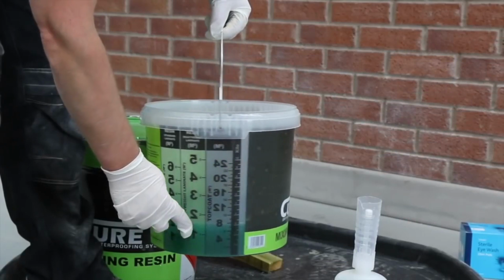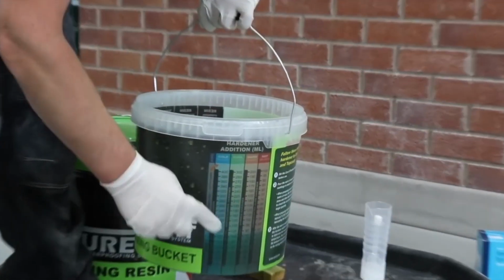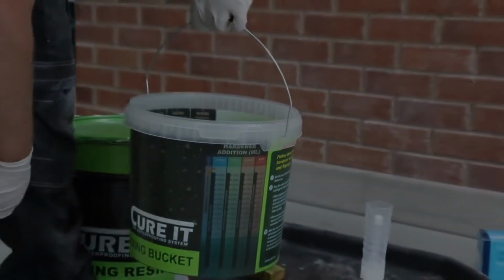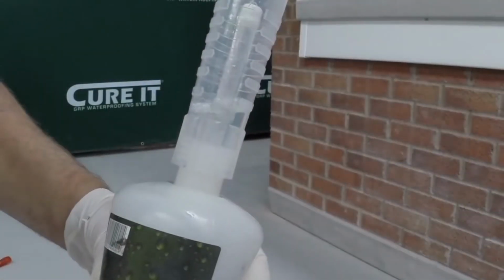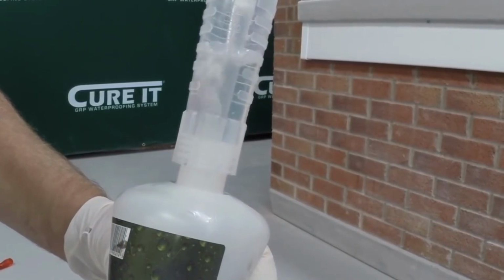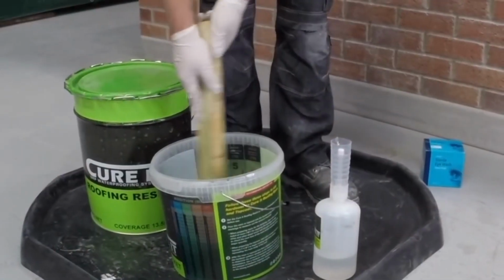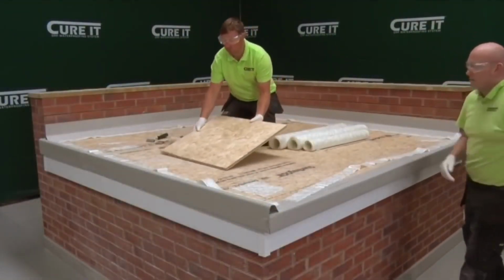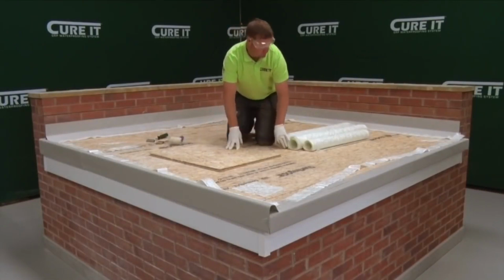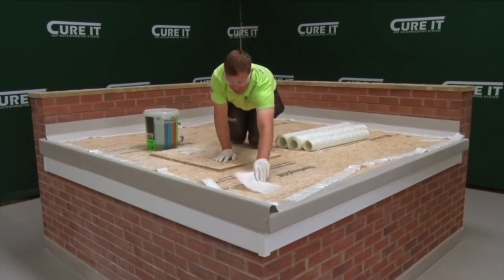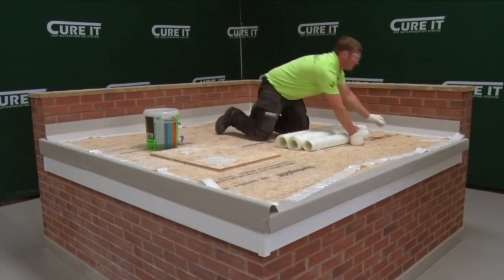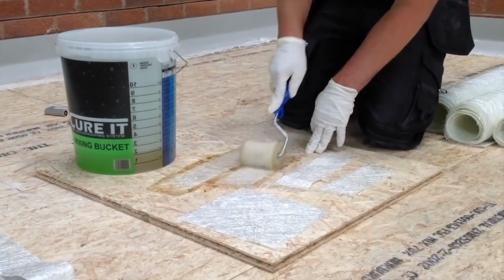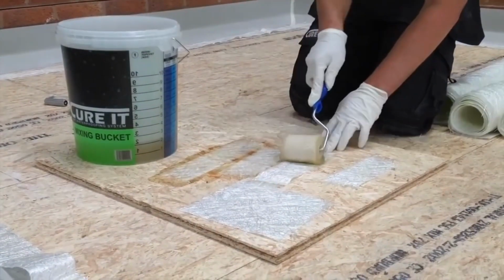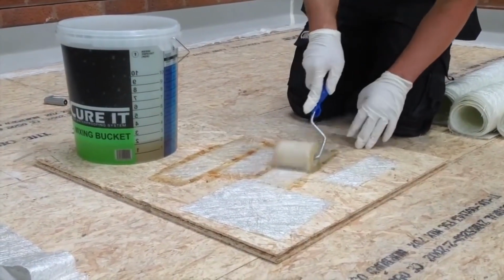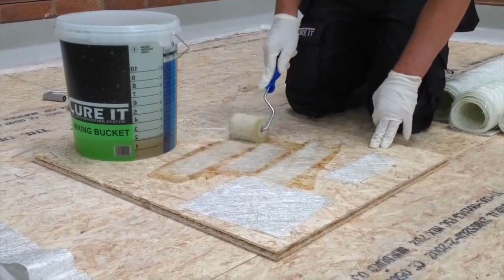Using the hardener addition chart on the side of the mixing bucket and factoring in the decking temperature and ambient conditions, measure out the required volume of hardener using the safety dispenser and mix thoroughly into the resin using a slate batten for at least 30 seconds. Set aside a dedicated area for wetting out the bandage using a spare piece of OSB board. Take the smaller lengths of bandage that have been set aside for corners and detail. Ensure the bandage is saturated with resin and transparent. The bandage can then be carried to each detail on the roof and laid over the top.